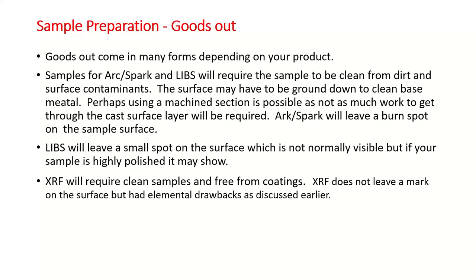ArcSpark will leave a burn spot on the sample, so you have to be very careful while you do the prep. Sometimes on a casting, you might be able to do it on a flange where it's already been prepped, so the flange has been machined. But sometimes that is a machined surface that is mated for a seal, so then you can't put anything on there that's going to burn a spot. So there are advantages and disadvantages to being able to do that.